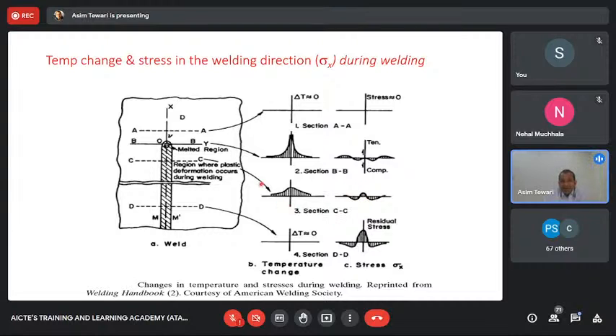However, when you are at location B, which is right on the pool, what you realize is that at location B, the stresses in the center are exactly 0. Why? Because everything has become molten. And then when you cool it down, you come to CC, this line, and what you realize is that now the temperatures are coming down, but now the center has started having a tensile residual stress. And by the time you're far away from it, the center develops a tensile residual stress and the regions beside it have compressive residual stress. Remember, going up is tensile residual stress, going below is compressive residual stress.